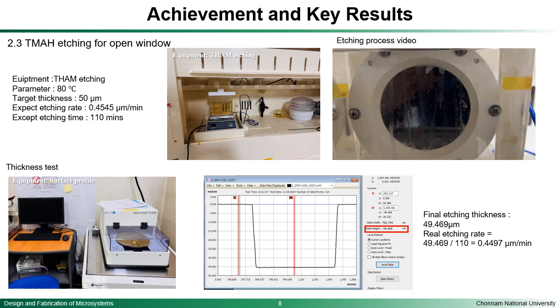silicon wafer. And after the surface profile, we measured the thickness of the etching, and the final etching thickness is 49.469 micrometer, and the real etching rate is around 0.44970 micrometer per minute.